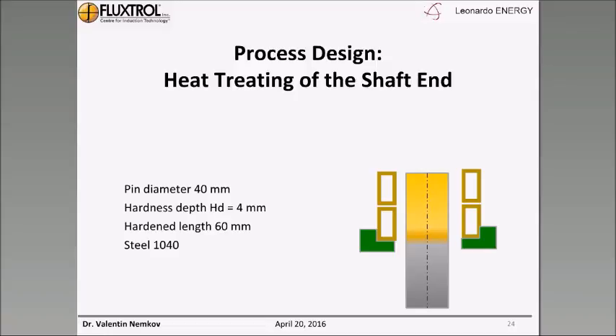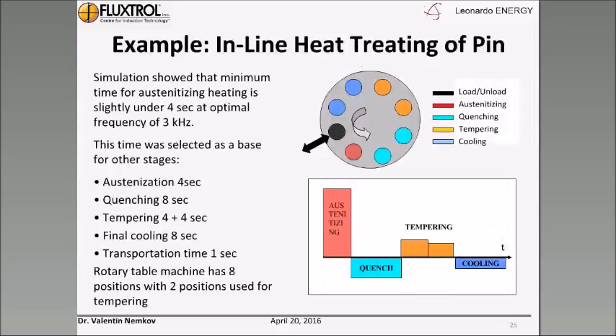Now, in simple cases, or as a preliminary stage for simulation, we can use an even simpler 1D approach. An example is heat treating of a shaft end with a diameter of 40 millimeters and a hardness depth of 4 millimeters. That's how it could be heated, and that's what we desire. We need to harden that, then temper that, and finally cool. By simulation using the 1D program ELTA, we found that the minimum time for austenitizing is 4 seconds at an optimal frequency of 3 kilohertz. This time was selected as a base for other stages.